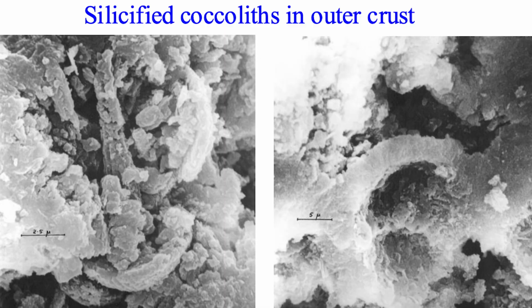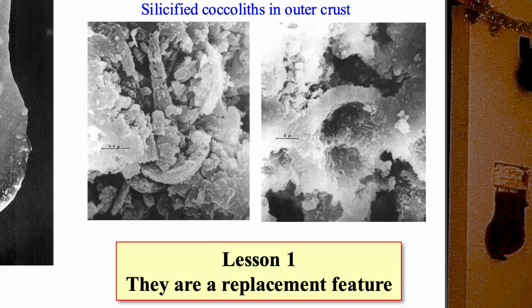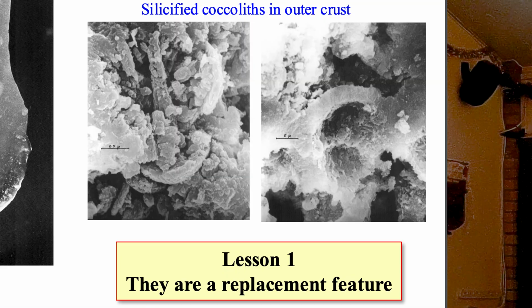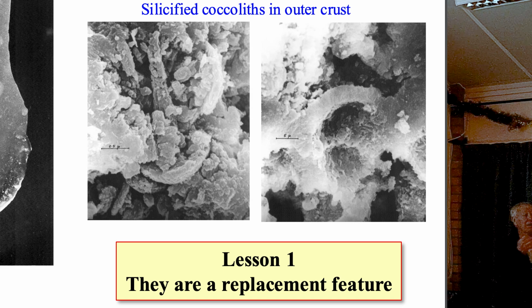So I looked at both of these samples, and everything you can see on the right there and on the left all gives a signature of silica, which is what the flint's made of. They're originally calcite from the chalk, so they've actually been replaced by silica in very, very fine detail. So the first lesson we should learn from this is that firstly, the flints are actually a replacement feature.